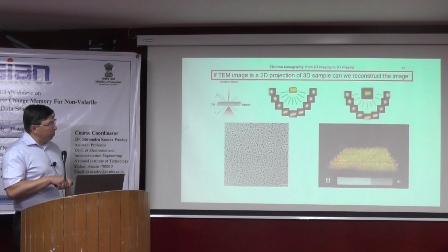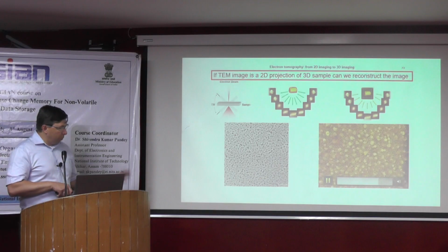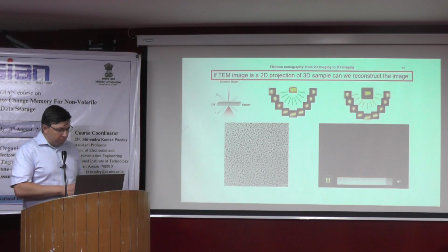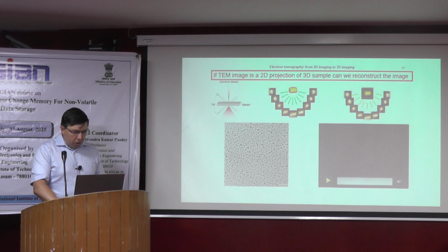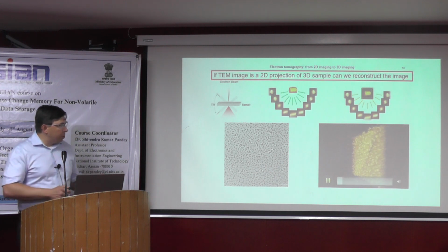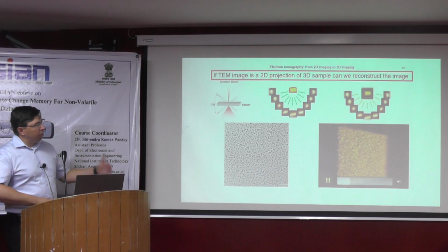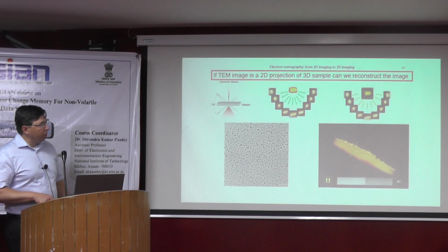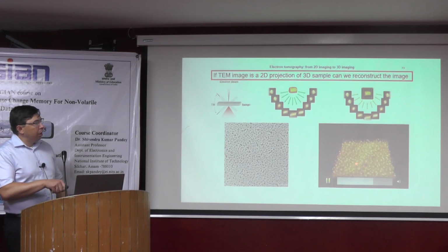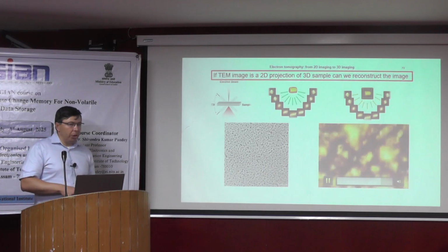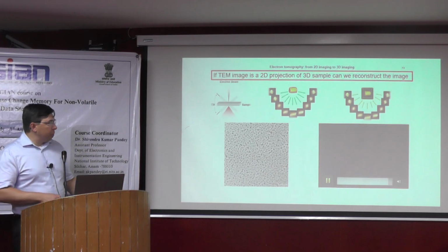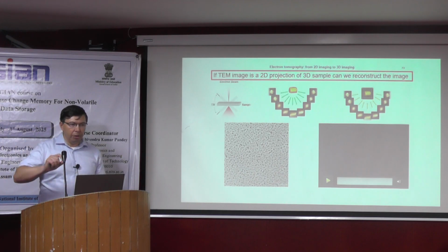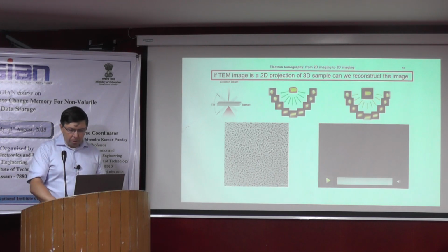So it was directly deposited on the carbon grid, on the grid covered by carbon. So there was no preparation in this case, only the image in tilting, and you can see again here that a larger fraction sits on one surface of the sample. And so if you have such a 3D image, you can also proceed with quantitative analysis of your images, like you can calculate the sizes, distribution in different places, and also the distances in between.